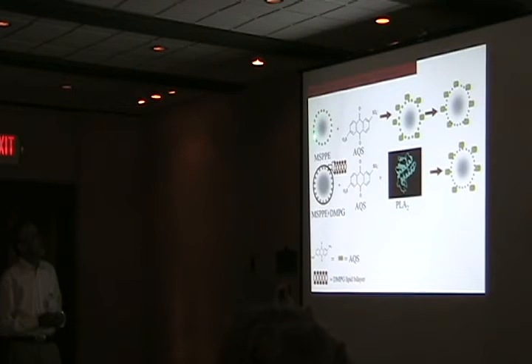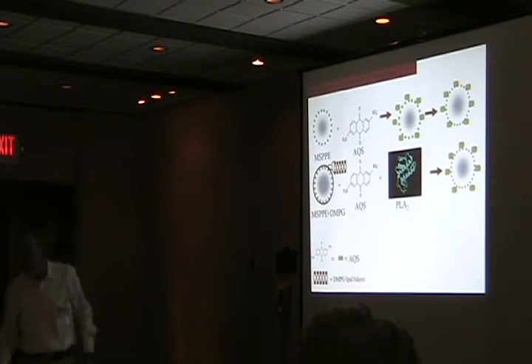So what we expected and observed is that we have the beads coated with the fluorescent polymer, and we add anthraquinone disulfonate. The fluorescence is quenched as the anthraquinone associates with the beads. What we hoped was that if we built a bilayer over this particle-supported polymer and now added anthraquinone disulfonate, there wouldn't be very effective fluorescence quenching. But now, if we added phospholipase and the phospholipase removed the bilayer, then we'd see quenching. And that's essentially what we found.